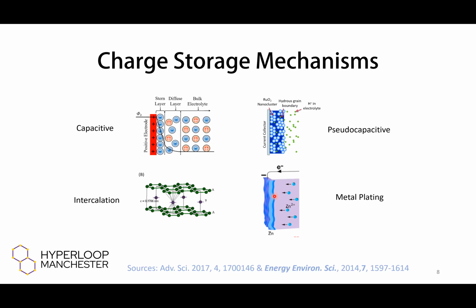And this, if uncontrolled, actually leads to dendrites and particles forming or coming out from the surface. They can pierce the separator and short circuit the cell. So it's actually a trick, or you have to finely balance and control the cell to make sure that you don't initiate the wrong charge storage mechanism, or you go past the limit and you might end up breaking the cell.